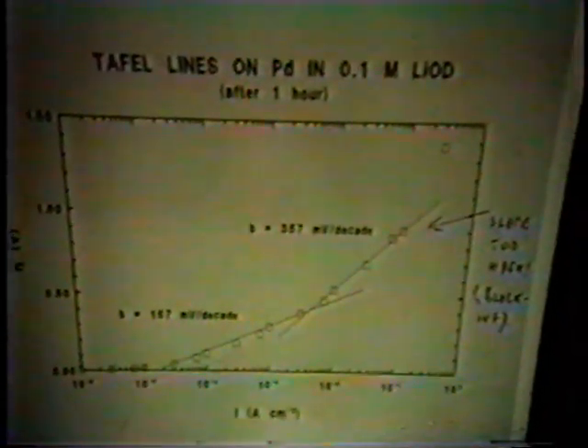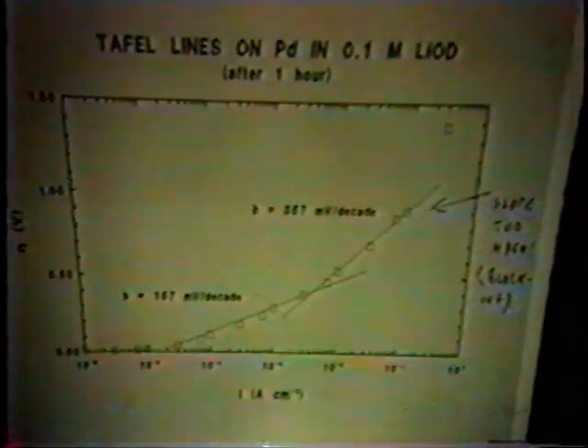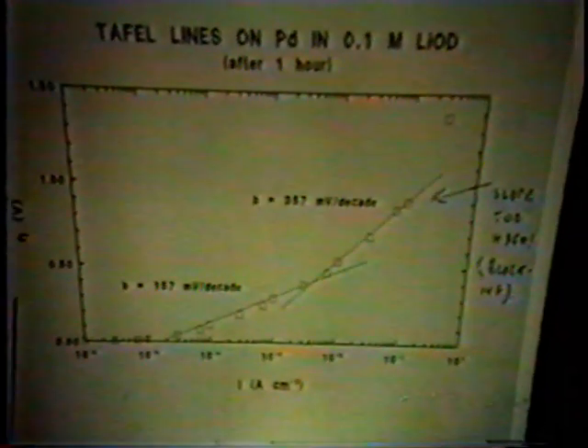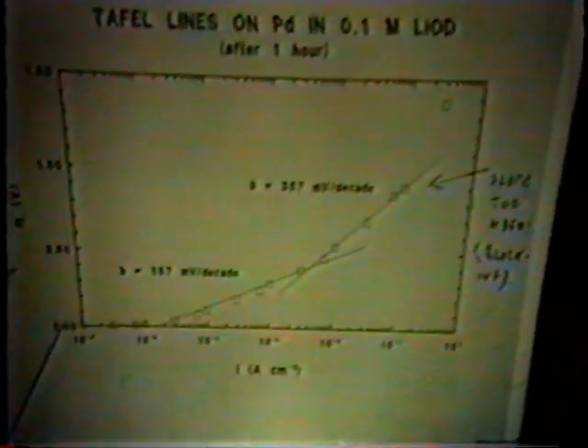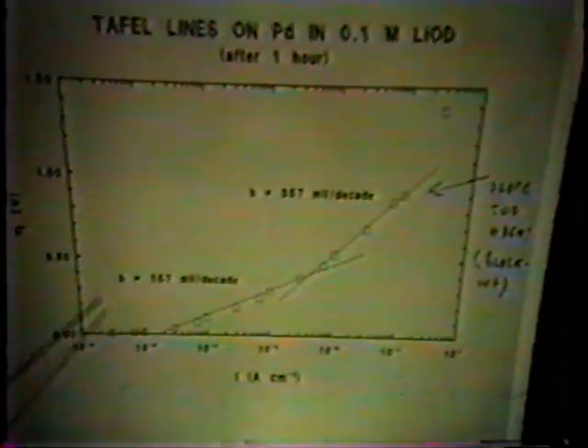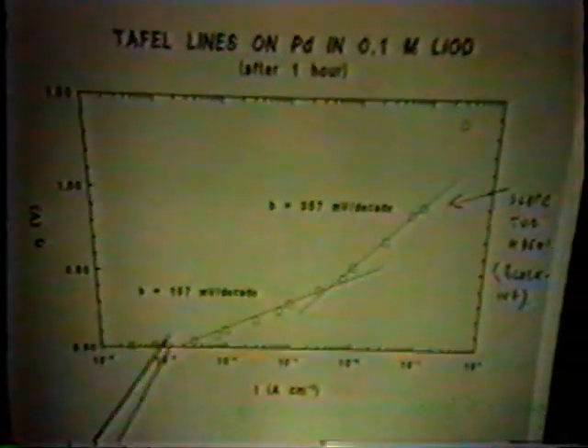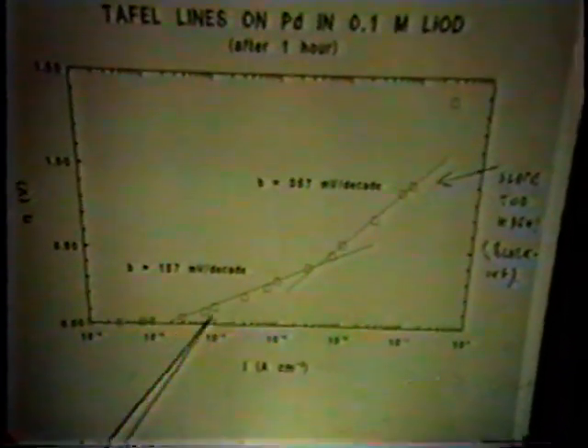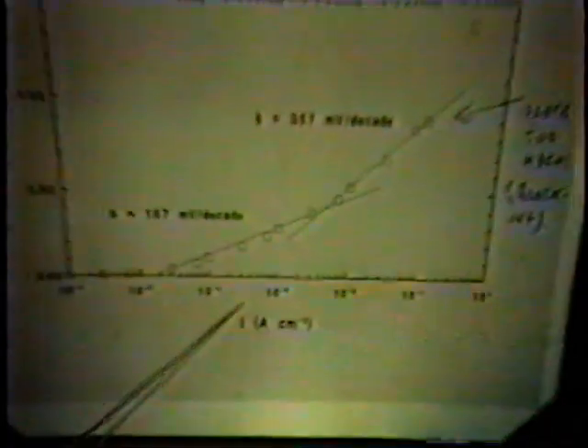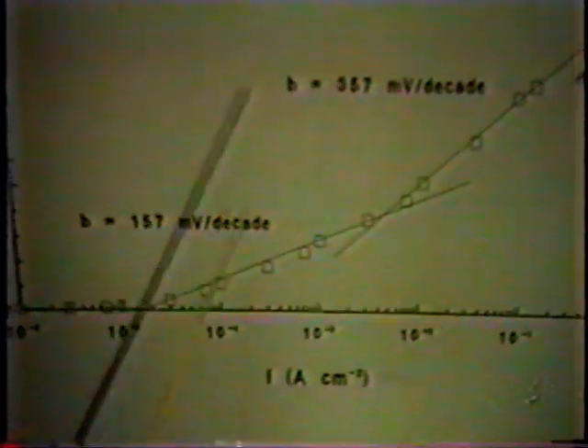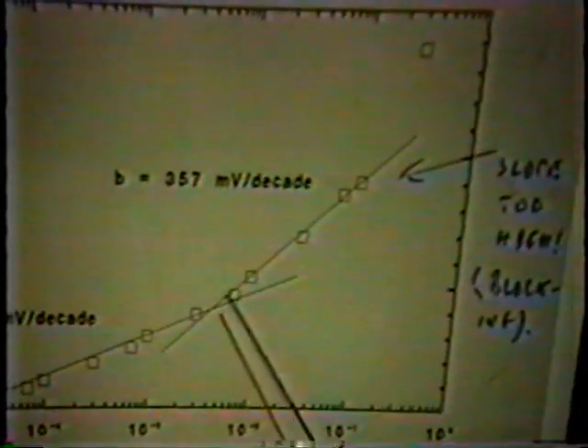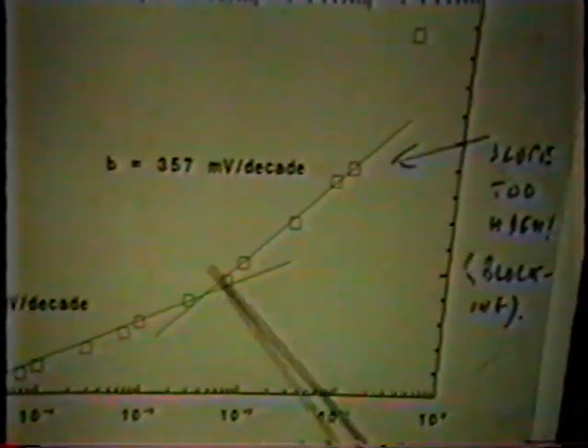So now let's look at what we call in electrochemistry the Tafel lines. And Tafel lines are, for electrochemists, PV equals RT, you might say. They're the standard electrochemical beginning of the technique of looking at mechanisms. What they are plots of is over-potential, the deviation from the reversible potential, as a function of the rate. So here we go, 10 to the minus 5. We go up here and we get an excellently straight Tafel line. That's what we want. We want a linear log I graph, a semi-logarithmic graph. And then we get a very sharp break. Another Tafel line. It has quite different properties.